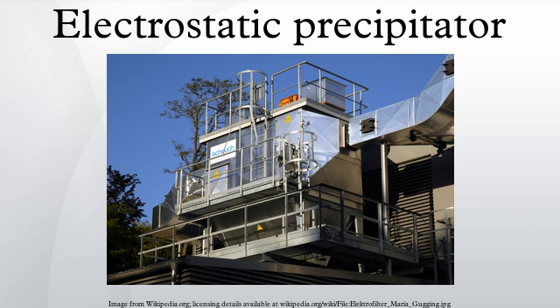Another problem that occurs with high resistivity dust layers is called back corona. This occurs when the potential drop across the dust layer is so great that corona discharges begin to appear in the gas that is trapped within the dust layer. The dust layer breaks down electrically, producing small holes or craters from which back corona discharges occur. Positive gas ions are generated within the dust layer and are accelerated toward the negatively charged discharge electrode. The positive ions reduce some of the negative charges on the dust layer and neutralize some of the negative ions on the charged particles heading toward the collection electrode.